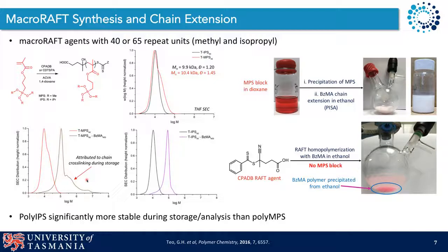We have to obviously precipitate and isolate the polymer prior to SEC, which greatly enhances intra and intermolecular cross-linking, and we end up with a lot of insoluble material that we can't analyse. We can see here over on the right hand side of the figure that if we perform our chain extension in the presence of our MPS block, it is indeed acting as a stabiliser. We get a nice clean colloidal dispersion as a result. If we don't have our MPS block present, we end up with a precipitate, of course, polybenzyl methacrylate not being soluble in the reaction medium.